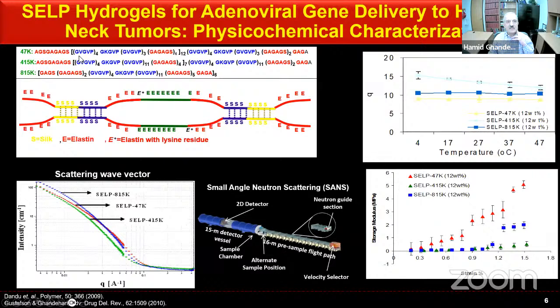And in this monomer sequence, for example, you can see that we have 4 elastin units, 1 elastin unit that has a lysine residue, and another elastin unit that is repeated 3 times, plus the silk units that are repeated 4 times. And the entire monomer sequence is repeated 12 times, plus some head and tail sequences. So in this case, we call this 47K, where you have basically 4 silk, 7 elastin, plus 1 elastin that contains a lysine residue.